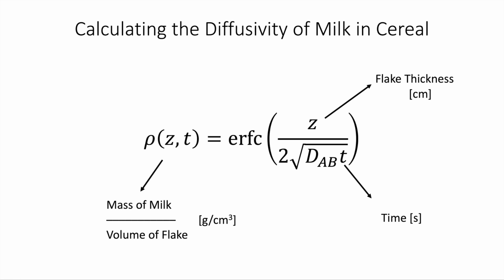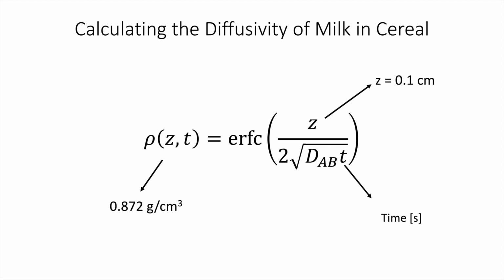So coming back to this equation, we have the mass of milk and the volume of flake, which we measured, and this comes out to be, on average, 0.872 grams per cubic centimeter. So essentially, for a saturated cornflake, there's about 0.872 grams of milk for each cubic centimeter. The flake thickness I mentioned previously was about 0.1 centimeters. And the time, well, we've already gotten those from our different experiments.